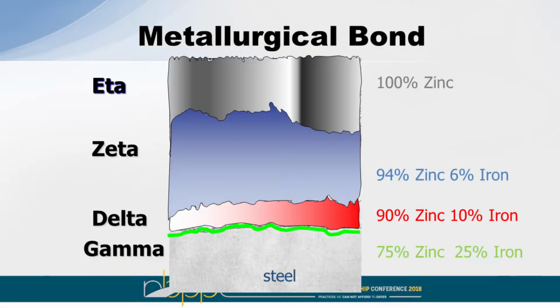When the steel is coming in, this is the metallurgical bond that is formed. So you have your base steel down here. You have your gamma layer coming in at 75% zinc and 25% iron. The delta then comes in the next level, 90% zinc, 10% iron. The zeta, as you can see, it's building out even larger here, 94% zinc to 6% iron. And then your eta layer, which is your free zinc layer, the 100% zinc layer.